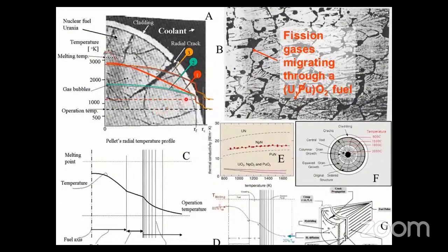Here, an important part is what the problems are in the actual nuclear reactors. The fuel is cracking. The fission products accumulate, making the fuel brittle, and they chemically react with the fuel. Also, the temperature distribution inside the fuel pellet makes it prone to cracking because of high expansion in the core, and ceramic is not so resilient. Also, as the materials have different conductivity, this is a complex structure of events that can happen in the actual nuclear fuel.